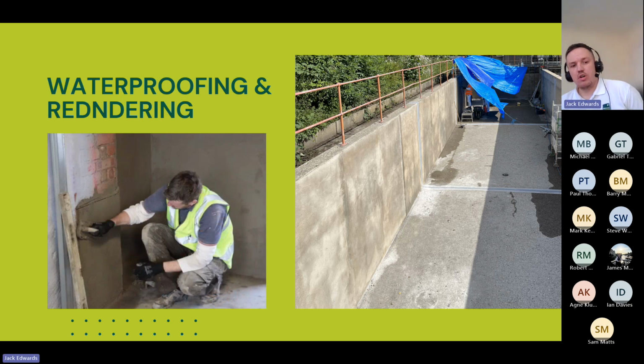Waterproofing or rendering. When the products are used for waterproofing or tanking, they're generally applied as a render. So we've got our NATCEM 35, NATCEM DW, NATCEM tank, all suitable, all applied as a render for a minimum of 10mm thickness. A 10mm coating of natural cement render, all good up to 10 bar hydrostatic pressure, which is a 100-meter head of water, so it's pretty strong stuff.